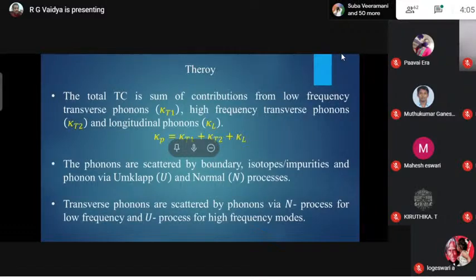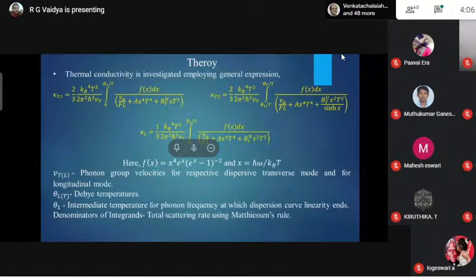So here we consider the low frequency transverse phonons are scattered only by normal processes, and the Umklapp process is observed to begin at half of the Debye frequency, at which the phonon velocity is observed to vary for black phosphorus, and that has been extracted from the phonon dispersion curve done using first principle calculations.